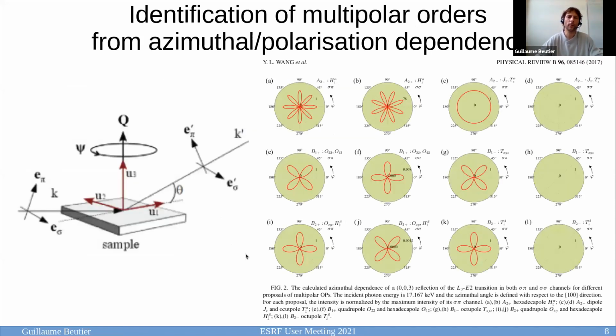So how can you identify the multipole that you measure, in case you're able to measure it? You can identify it through the polarization and the azimuthal dependence of your diffraction signal. So the idea is that if you're measuring a diffraction peak in direction Q, you can make a polarization analysis of your scattered signal, either keeping the same polarization as your incident beam, or probing the rotated channel, and you can also rotate your crystal around the diffraction peak, and you will see different symmetries of your signal depending on the multipole you probe. So this has been nicely described in this paper actually, although experimentally they didn't find anything, but this is the theory.